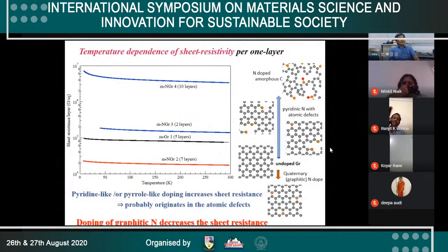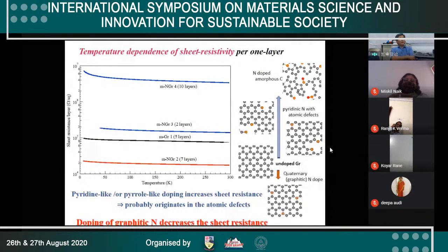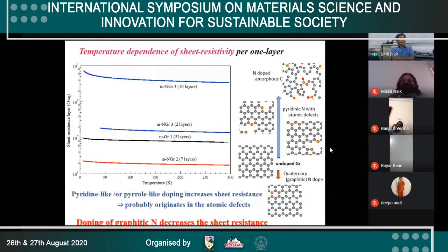Next slide, please. After making the film, we removed the sample from the copper foil and transferred it onto a quartz plate and put on four terminals in order to measure the temperature dependence of the electric resistance. The result is like this. The black line, MGR1, is a non-doped sample, meaning no nitrogen doped. The resistivity shows almost no temperature dependence between about 10 Kelvin and 300 Kelvin.